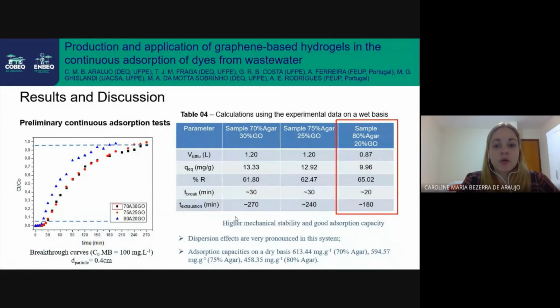And we also proceeded with some preliminary fixed bed adsorption tests for all the 3 samples. Overall, it can be seen that over 800 milliliters of effluent was treated in all cases. And the sample that presented higher mechanical stability and good adsorption capacity was the one produced with 20% of graphene oxide only.